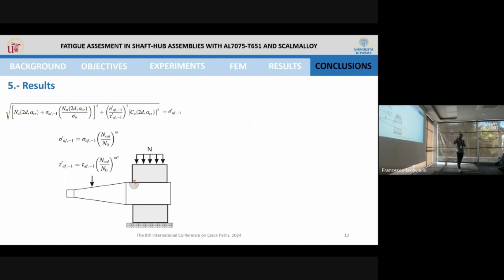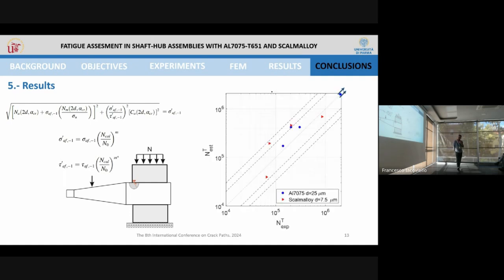So after applying this to all our results, we compare our predictions with the experimental results. On the x-axis, we have the experiment results. On the y-axis, the estimation. The dotted lines are scatter 1 for 2 and for 3. All of the results lie inside scatter 1 of 3, and most of them inside scatter 1 of 2. So you can say that the model works well despite the complexity of the whole assembly.